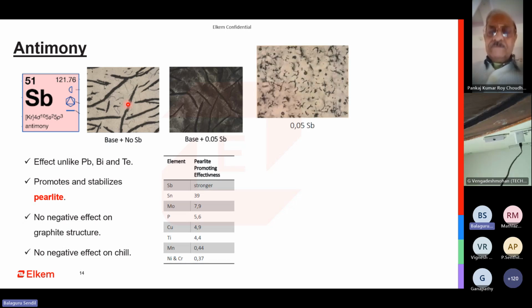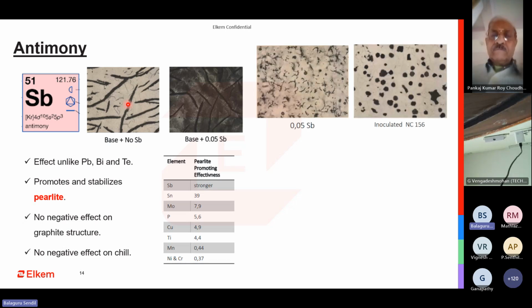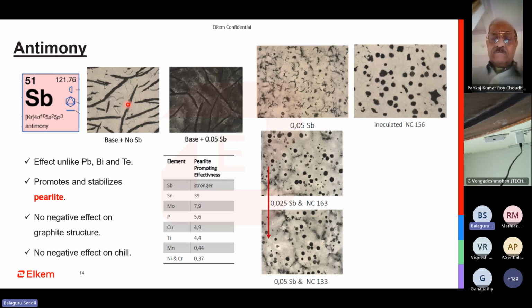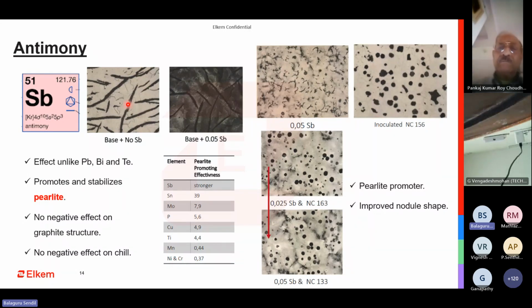But when it comes to ductile iron, we all know that when you are having antimony, you can actually break up chunky graphite. When you are having heavy section casting, people advise adding antimony so that you don't have all the nodules joining together. When you have sufficient cooling time, that is in the thick section, all the nodules will join together, form a big nodule, and then still it has sufficient time to cool, it can form chunky. So to solve this problem, there is a typical suggestion to add antimony, but it promotes pearlite along with it.